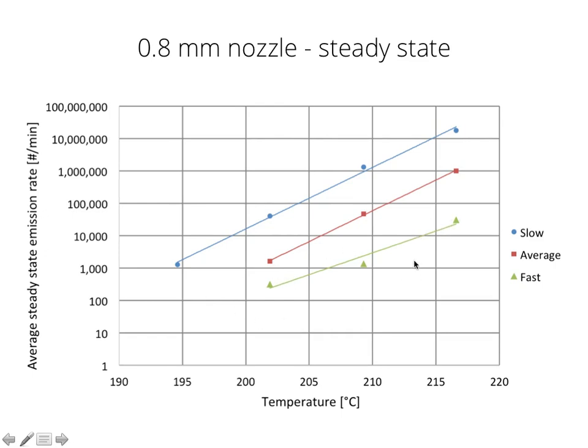But as I already mentioned, due to the high volumetric flow rate that exceeded the V6's capabilities, we don't get a good fit of the exponential function. What is interesting to note here is that the slow printing speed, or the average printing speed, is just shifted slightly to the right. So you can see here that these emission rates are basically on the same level, which I find interesting.